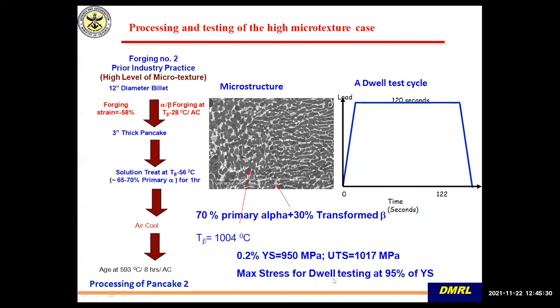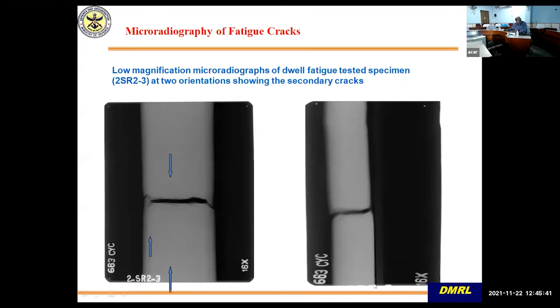And these are the stress levels at this is 0.2% yield strength, 950 MPa. So it was tested. Maximum load was 95% of that. So this was tested on a flat sample, and you can see this flat sample micro radiography was done.